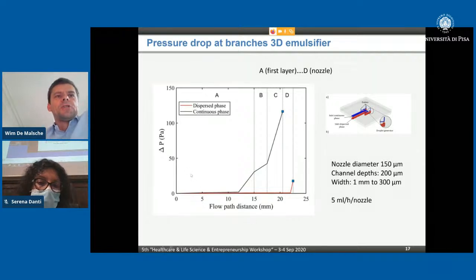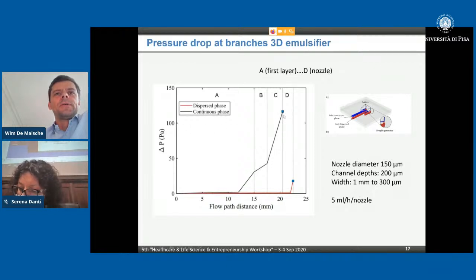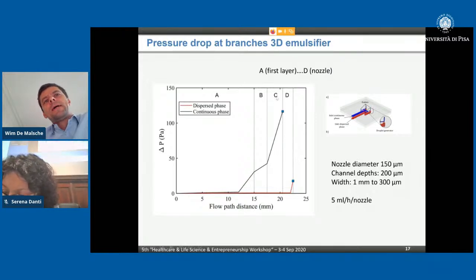Now, coming back to this pressure drop: if we have a single nozzle at 5 ml per hour, you can see that we are at 1 millibar more or less on pressure drop. But what is interesting here, and this was not the first design that we made, I don't have time to go too deep into it, is that this is the first channel, the second, the third, the last for one of the phases. And you can see that we have the highest pressure drop in the last branch. This is relevant because it gives us a forgiving effect on fouling.